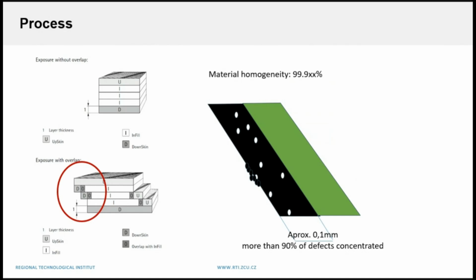So in our department, we're looking for another solution during the process, how to optimize and how to minimize the internal defects on the basis of neural networks and an adaptive system, which could remelt the problematic area, because during our process, every time one layer is printed, the melt pools are remelted 2.5 printed layers before.